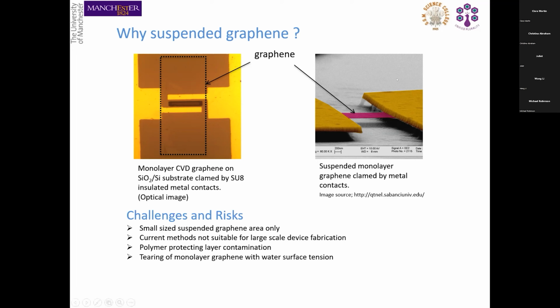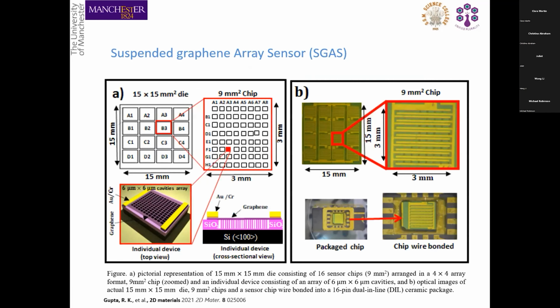You cannot make a large number of suspended structures because this is a single atom thick film. As soon as the area or the length of these strips gets bigger, they will sag down and touch the surface. So it's very difficult with the current traditional method. You cannot make large area suspended graphene structures. And also it tears off because of the water adhesion. So we came up with a new methodology in order to get a high yield in the suspended structures.